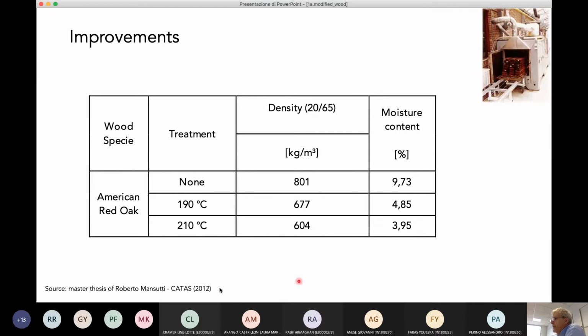This is a thesis we carried out some years ago with a student of the University of Trieste. We tested American red oak treated at two different temperatures. You can see here 190 degrees and 210 degrees. This is the natural American wood without any treatment. You see that the density is reduced by the treatment simply because the moisture content is reduced. Around 10% is removed for the non-treated wood, and more or less half of that for the treated wood.